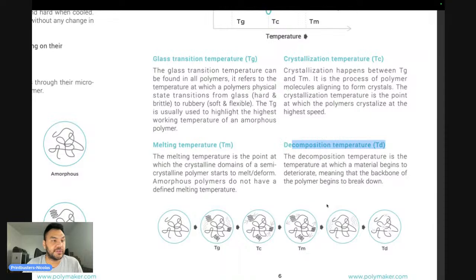And for some materials, you have different maximum crystallinity degrees. Let's say you take a nylon, and maybe the highest crystallinity degree is 30%. After printing, you only obtain maybe 10%. Then you anneal it in order to reach the maximum crystallinity degree, which would be 30%. So you go from 10% to 30%.